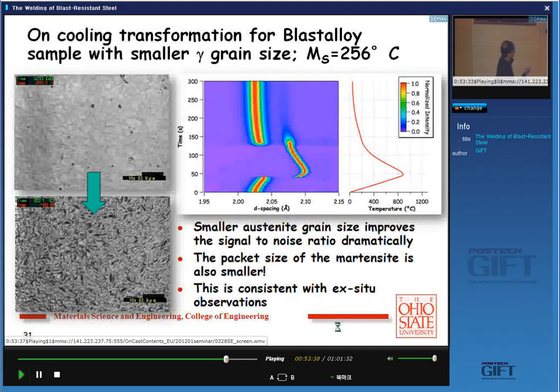Regarding a question about peak sharpening in the diffraction data before transformation: we looked at the lattice parameter distribution and don't think it is compositional inhomogeneity because carbon is very low. It may be due to surface straining — that is the only hypothesis we have and we don't have a way to prove it yet. We do see that sometimes the peak sharpens on cooling before the transformation occurs. Greg Olson thinks it's probably some soft phonon mode, but we don't know.